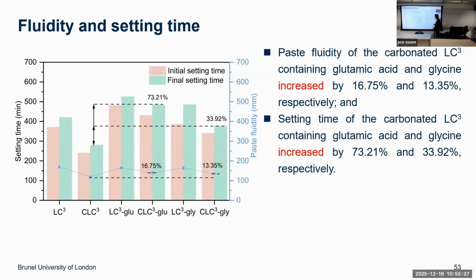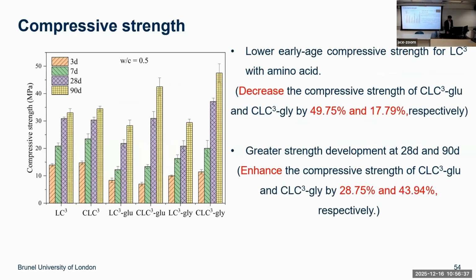And we found that initially, you can see the setting time, and also the final setting time. Roughly you see that the initial setting time is around 200 to 400 minutes. The final setting time could go up to 550 minutes. So the fluidity of the carbonated LC3 containing glutamic acid and glycine increased by 16.75% and 13.35%, respectively. That's the fluidity, which is better. The setting time of the carbonated LC3 containing these two amino acids increased much more. Remember, earlier we said injecting carbon dioxide into the clinkers in LC3 could cause faster setting. So with this amino acid, we can delay the setting and give the operation time for further operations.